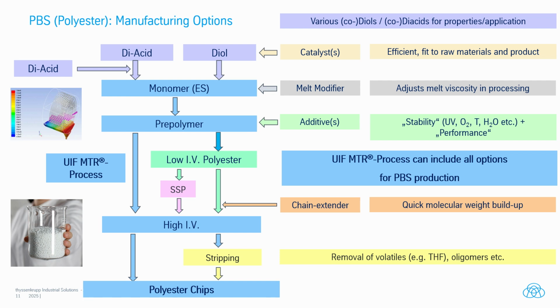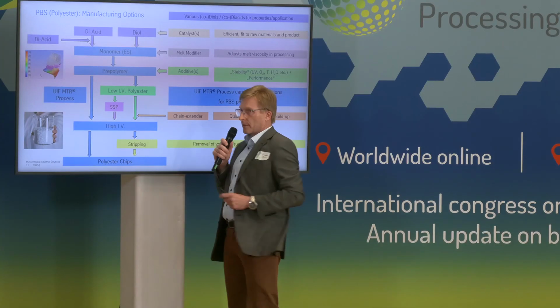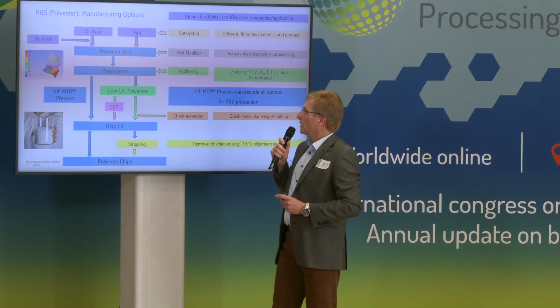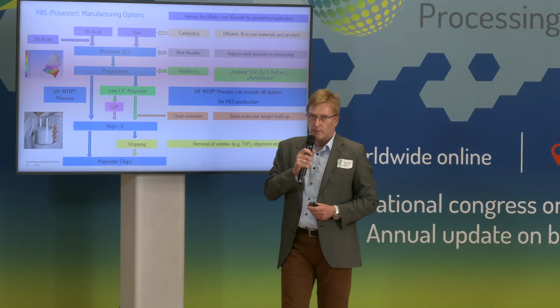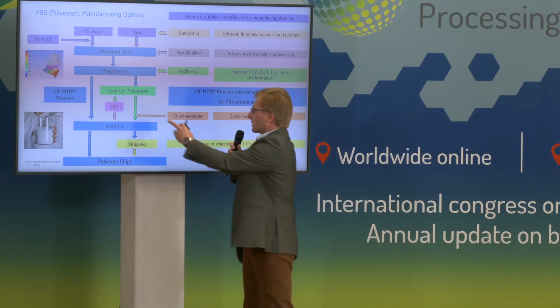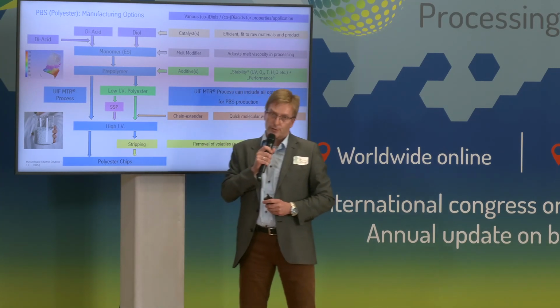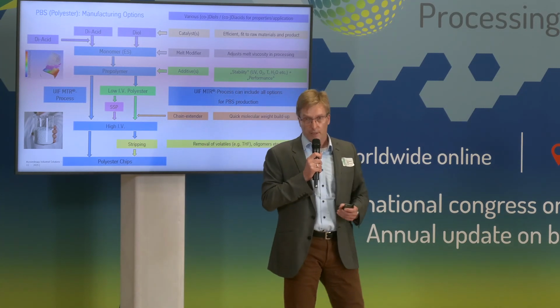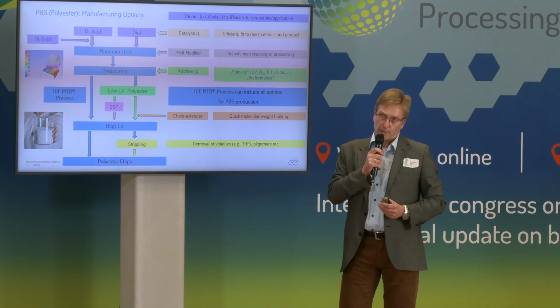Typically in the past, you would have produced a low viscosity polyester from this pre-polymer, and this would then have gone into an SSP, as I said, a solid state post-condensation process. But this is not a good idea for PBS because of the low melting point of the PBS.